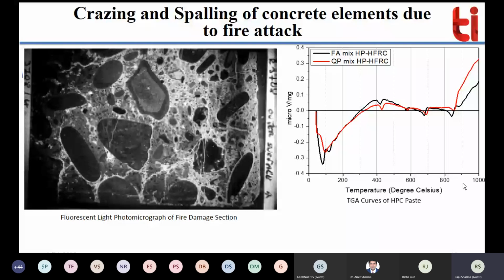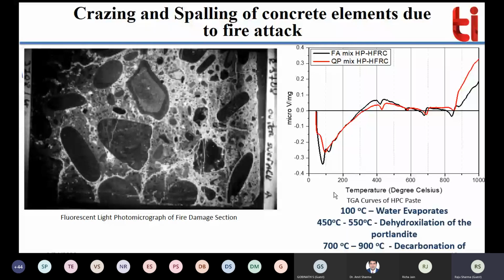So your material is subjected to the high temperature range, right? And then you can see, I will just show you first the minimum requirements, a general trend of the concrete against the heat. So if you see here, 100 degrees Celsius, water evaporates. It is general, right? Now 450 to 550 degrees Celsius, it is dehydroxylation of the Portlandite. Okay, so dehydroxylation of the Portlandite has happened. Now 700 to 900 degrees Celsius, decarbonation of the calcium carbonate has happened. So all these phases happen when you increase the temperature.